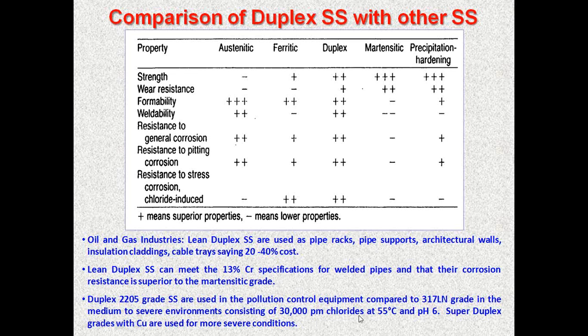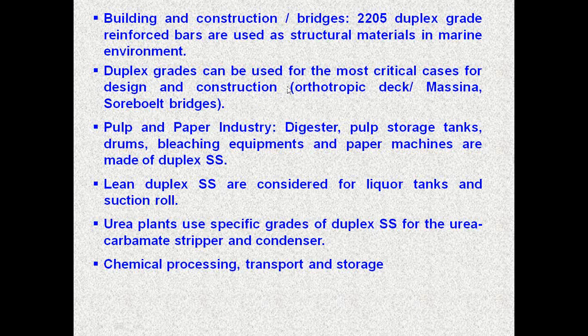I'm sorry, it is ppm chlorides, even up to a temperature of 55 degrees Celsius and pH 6. And also used in building and construction, the rebars, or it can be used also for design and construction of the decks and bridge component parts. Pulp and paper industry is the most benefited one. All the digesters, pulp storage tanks, drums, bleaching equipments, where a very high chloride and sulfate combination is there. And lean duplex, the most common one, is used for liquor tanks and suction rolls in the paper mill.